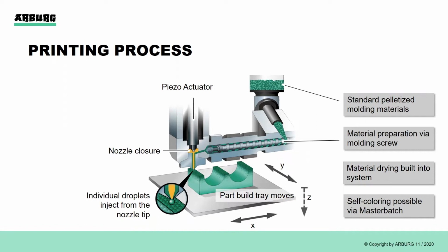The droplet discharge is synchronized with the movement of the tray, resulting in discharge frequencies of up to 300 droplets per second. Typical layer thicknesses that can be realized are in the range between 100 to 300 micron.